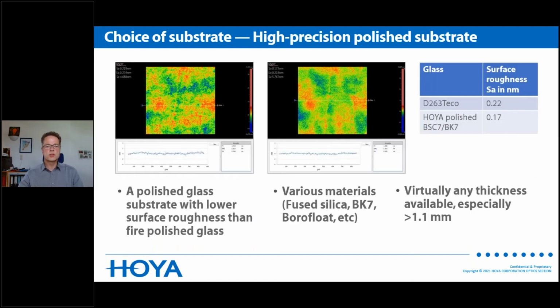One possible solution that Hoya can offer is high precision polished glass. The advantage is that it can be polished from virtually any of the known materials, and the surface quality, the surface roughness, can even be better than that of float glass D263 T Eco, as you can see in the two plots. On the left-hand side, we have the fire polished glass, and on the right-hand side, we have the high precision polished glass substrate.